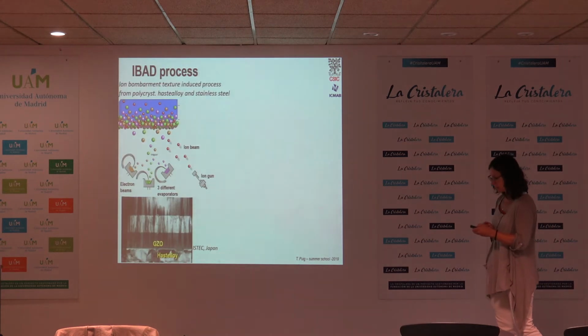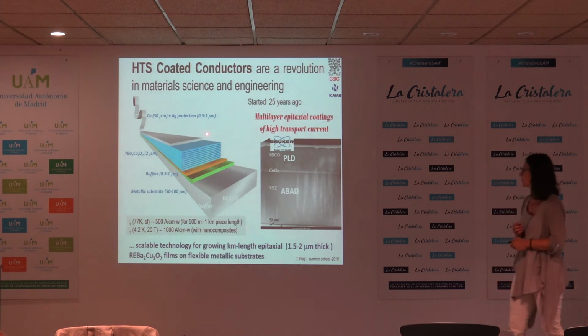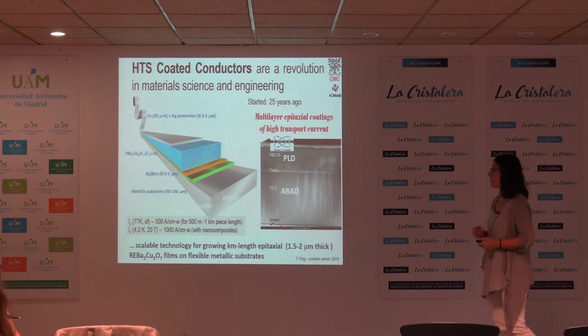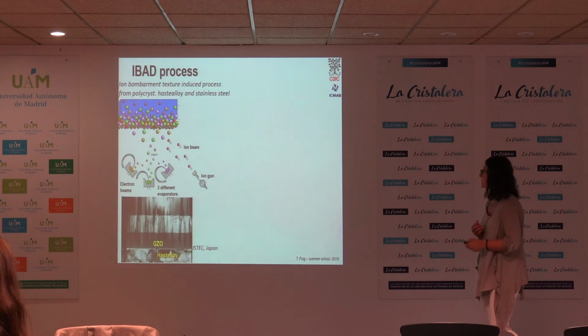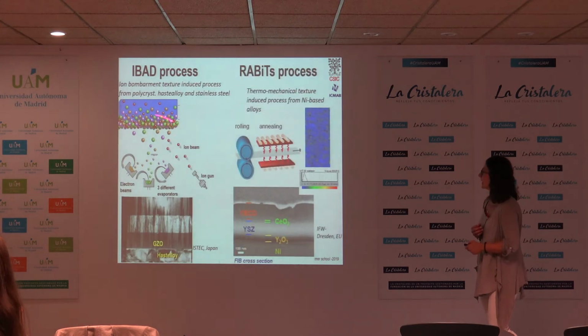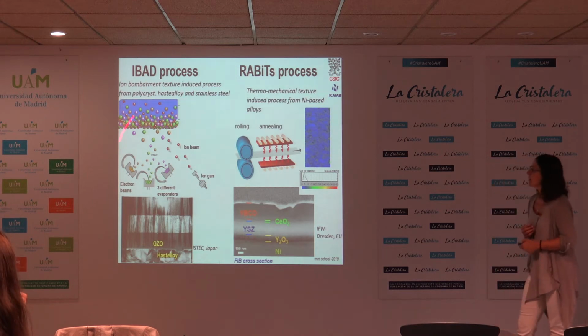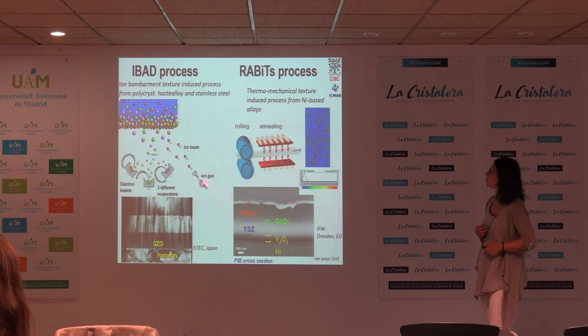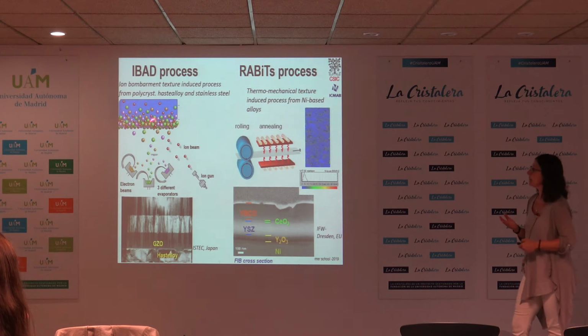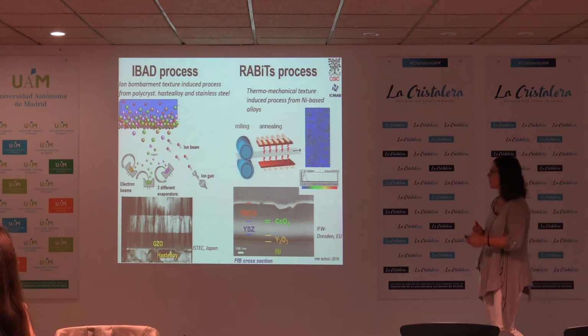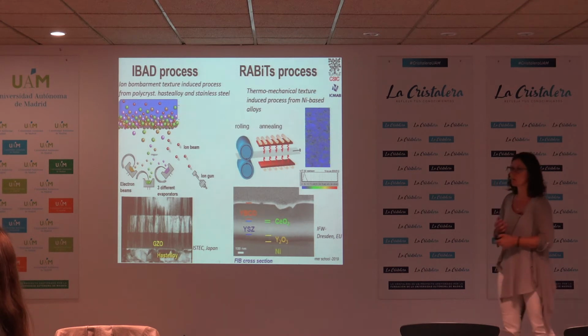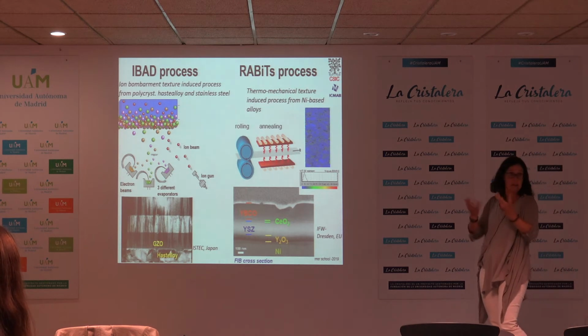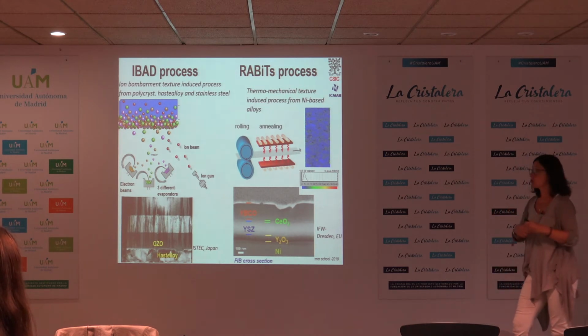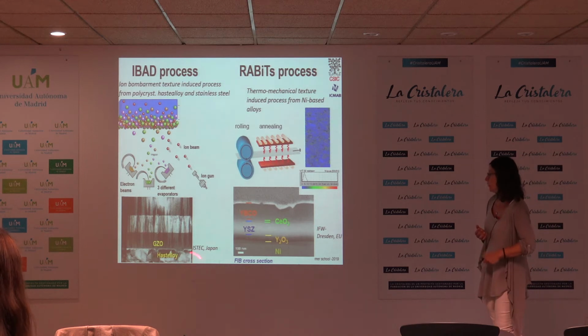Of course, one of the main problems is that the substrate, because we have to grow it epitaxially, somehow has to be textured. However, this is not easy, and what was demonstrated is that there are several techniques which are able to start with a polycrystalline substrate and then get it into texture, and that is the sputtering technique. This is called IBAD. This is ion beam assisted deposition, sputtering the ions of a buffer layer, while another ion beam is sent to the material, rejecting the orientations that you don't want, so that at the end you are able to grow an epitaxial layer on top of a polycrystalline layer.